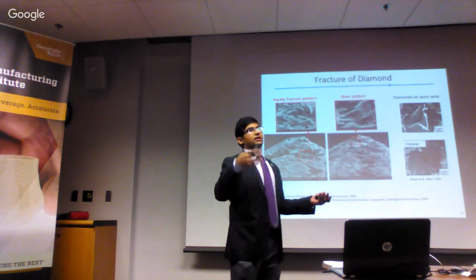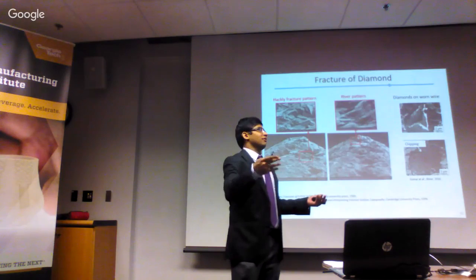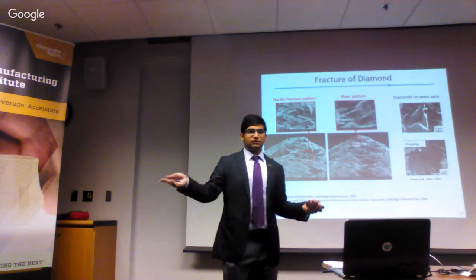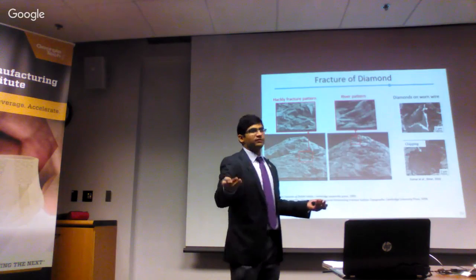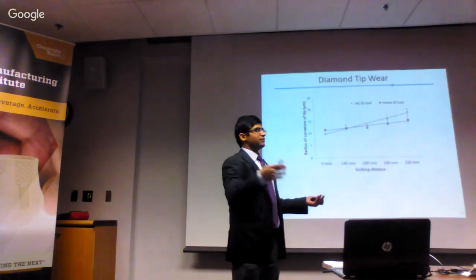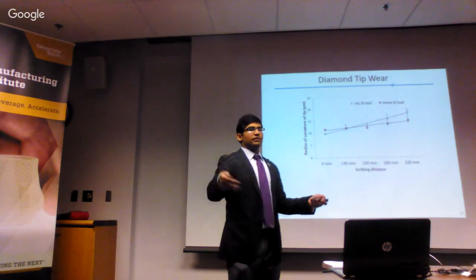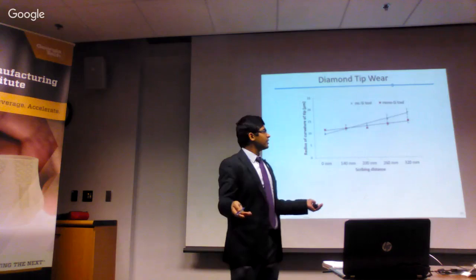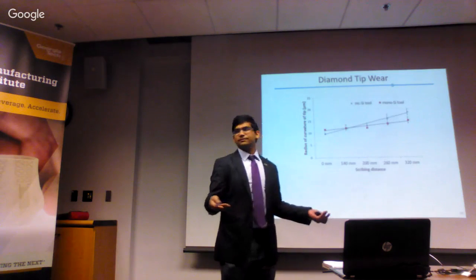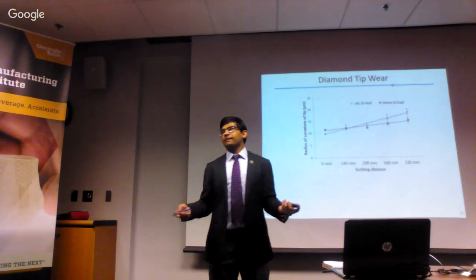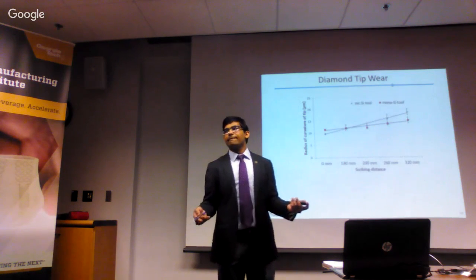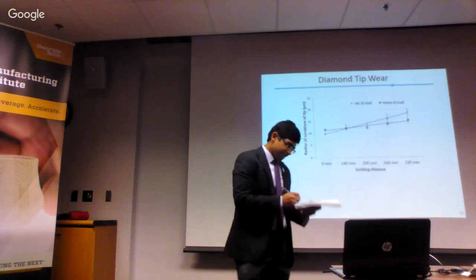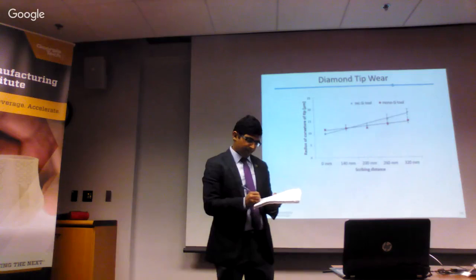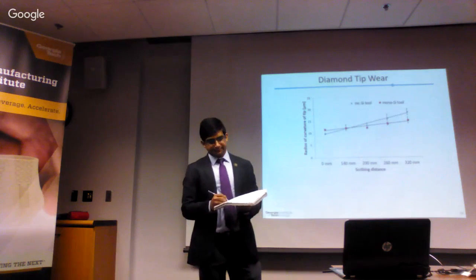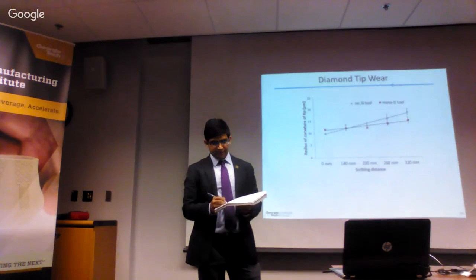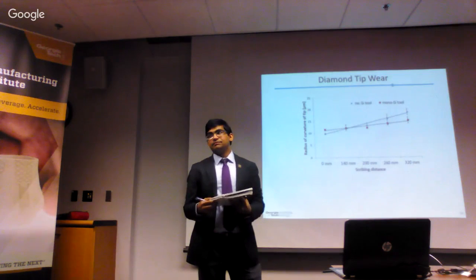I'm just making the point here that multicrystalline silicon wears it more, or creates more forces, which is expected to create more stresses, applied stress as well as residual stress. And the radius of curvature of the tip is rounder, or it's blunting more when cutting multicrystalline compared to mono. Would you say that if you had gone a longer distance, since it's just 320 millimeters, you would expect that difference to grow, and maybe the confidence level of your conclusions about the residual stress in particular to be greater? Anyway, that's my question.